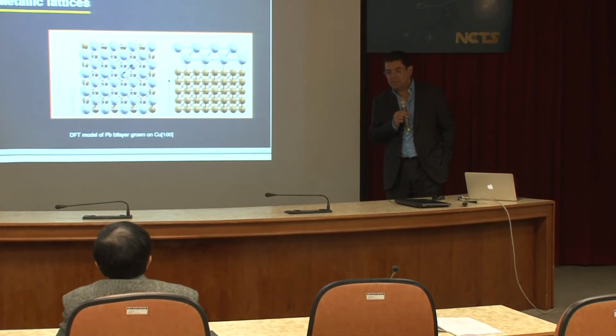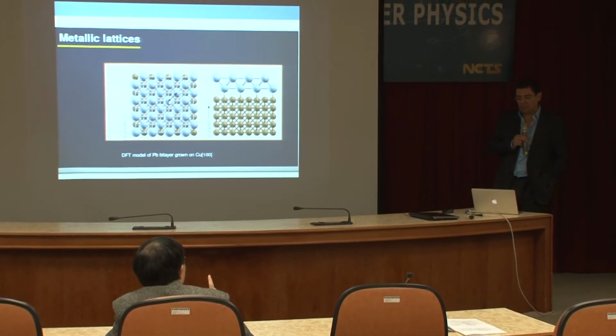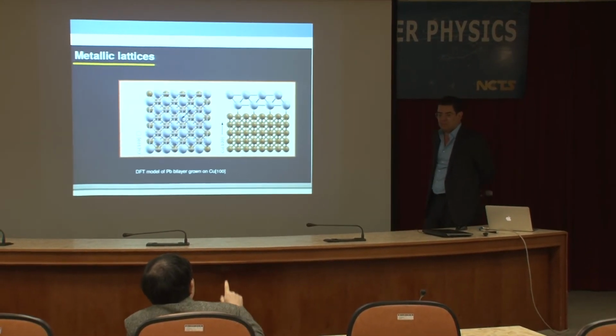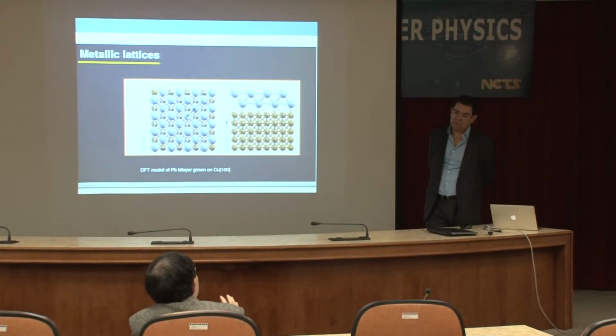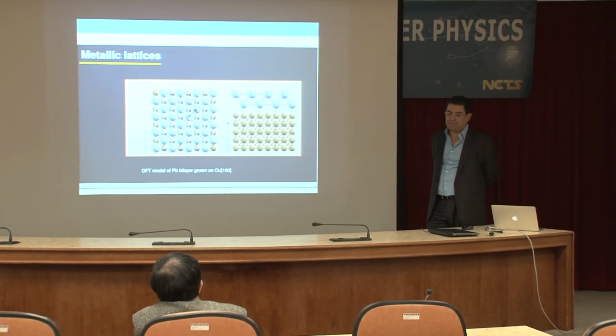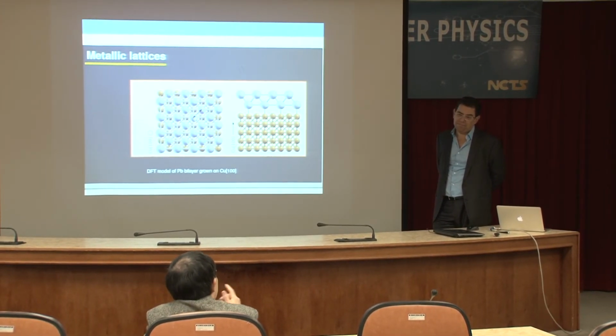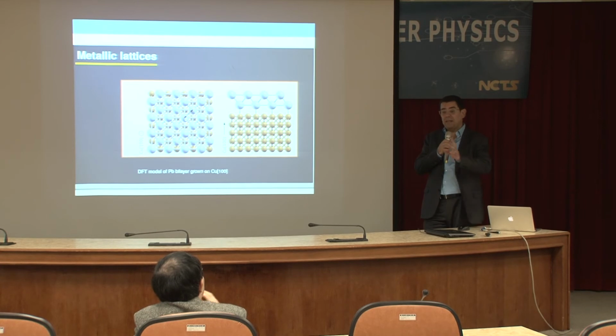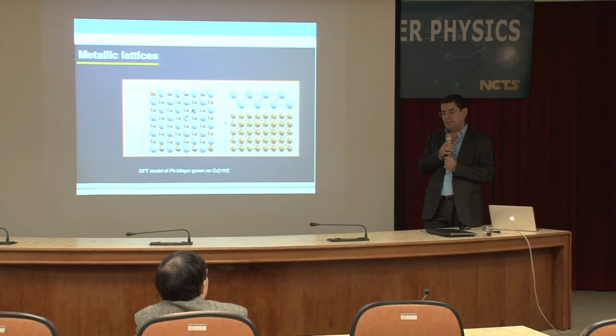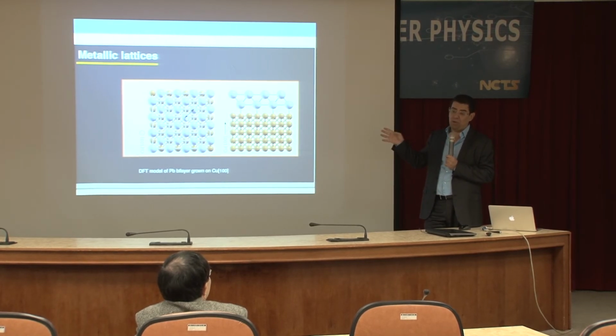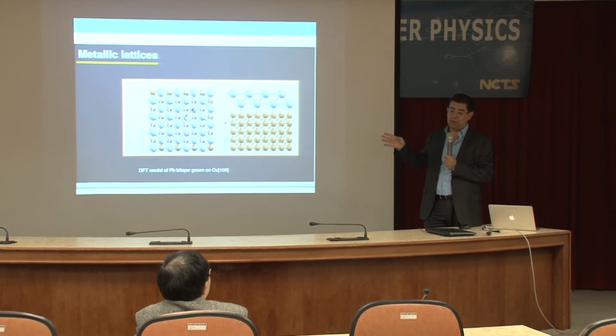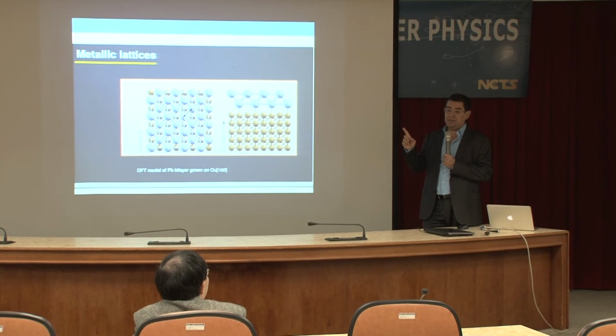Two questions. One is this group 4 monochalcogenides you mentioned. You show that the exciton can change quite a lot going from sulfide to selenide. Is that because the orbitals are more extended? Yes, exactly. Now my question is that experimentally you see very strong excitons in molybdenum disulfide. I guess that's because it's a direct band gap. Yeah, there are many differences here. What happened to gallium monoselenide, because it's an indirect band gap? Do we still see strong excitons in optics? Yes, in all these monochalcogenides, you see very strong excitonic response. But that's theory, isn't it? I wonder whether it's dark exciton or visible exciton.